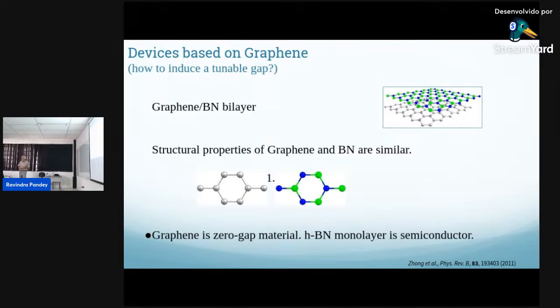The boron nitride is a semi-ionic compound. The ionic bonding is different, chemical bonding. And it's also a semiconductor. So our expectation is, look at the boron nitride and graphene. This carbon sees boron, and the other carbon sees nitrogen. So this interaction with carbon-boron, carbon-nitrogen is going to give inhomogeneity in the electronic distribution of these carbon atoms, and you're going to have a band gap. That's the hypothesis. So we did a lot of calculations.